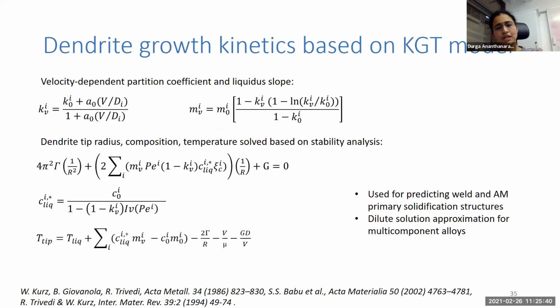So this is where the effect of the morphology and interfacial energy that I talked about earlier comes into play. And of course, we need to also include the non-equilibrium effects. In order to do that, we use this KGT model for predicting the dendrite growth kinetics, where we again use this velocity dependent partition coefficient and also liquidus slope. Then we can also calculate the dendrite tip radius, composition, and the interface temperature based on stability analysis. Since we already know that we have this cell structure forming, we did these calculations for the delta BCC and the FCC phases. This kind of model has been used for predicting weld structures and also AM structures, like predicting the primary solidification structure. But I should also point out that these models still use the dilute solution approximation for multi-component alloys.